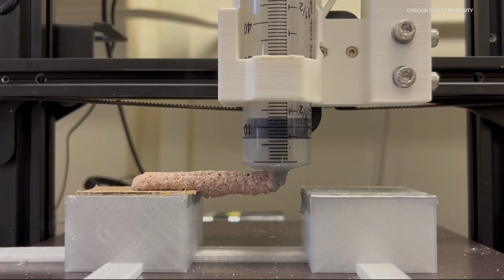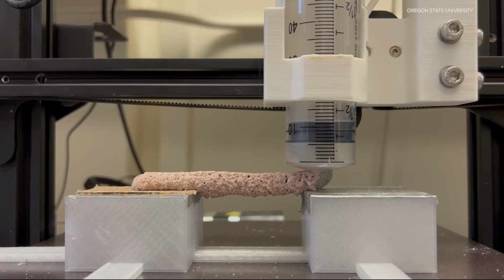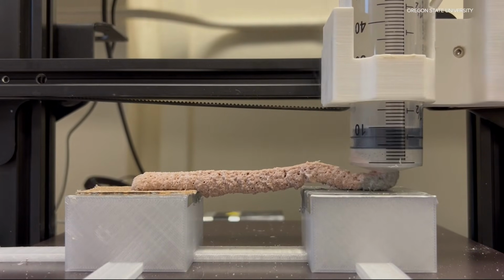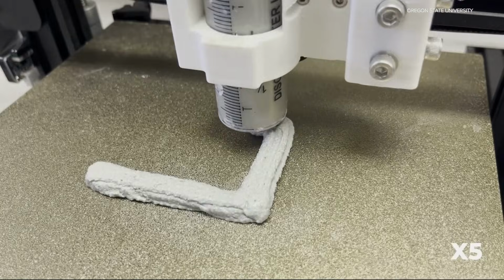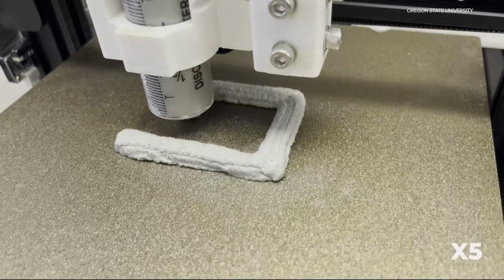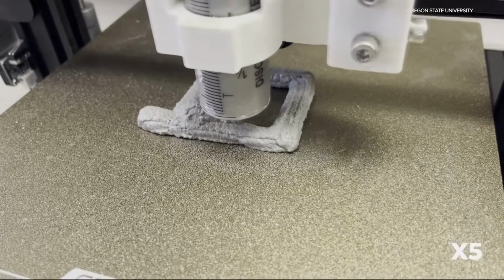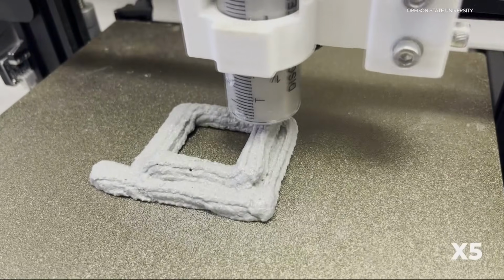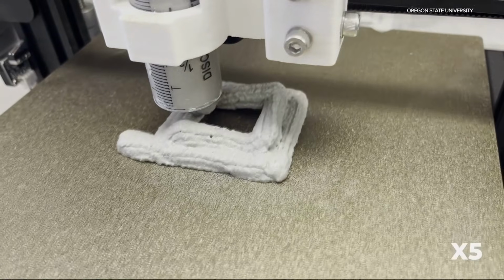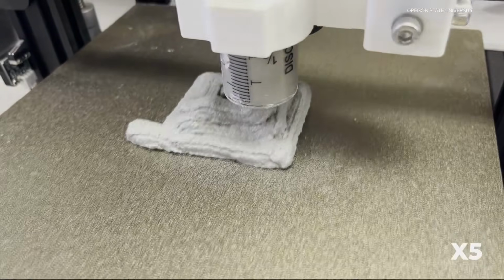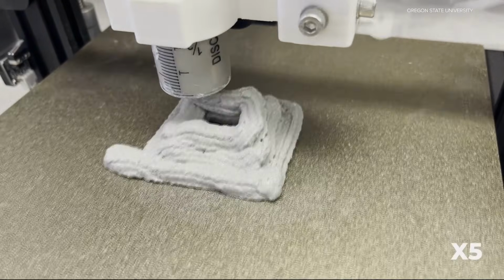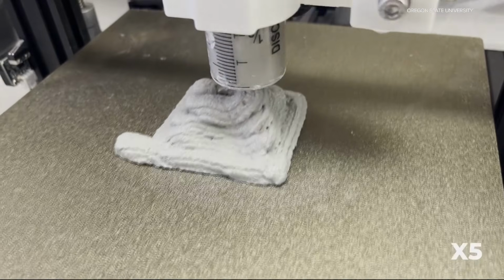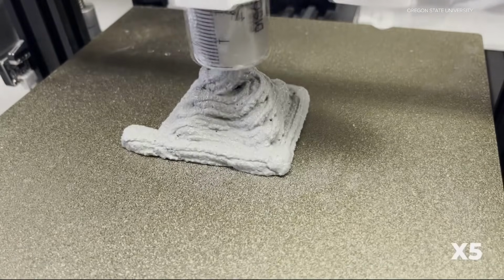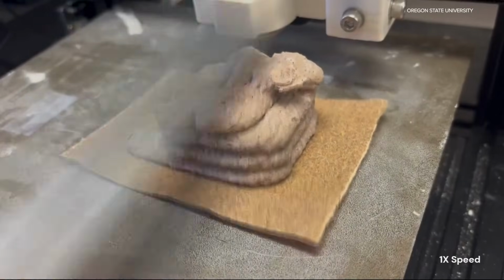In my lab in the past year, we've developed a 3D printable clay-based concrete, which can be immediately cured right after it's 3D printed, and it can be used for building of housing, infrastructure, and things like that. And the amazing thing about our material is that it's using clay and soil, which can be sourced locally at the construction site. Instead of relying on cement, the new material uses local clay and soil mixed with a small amount of special polymer binder that hardens almost instantly.